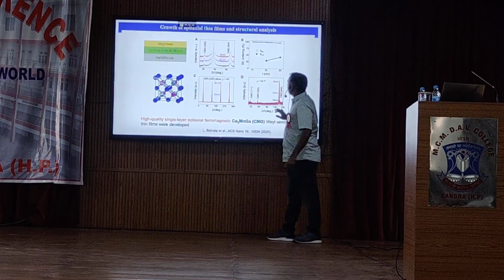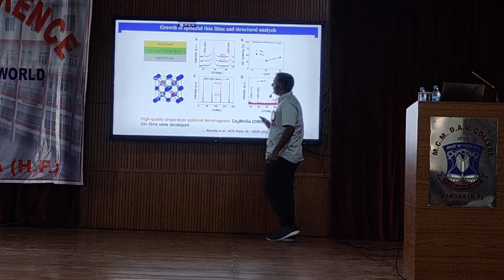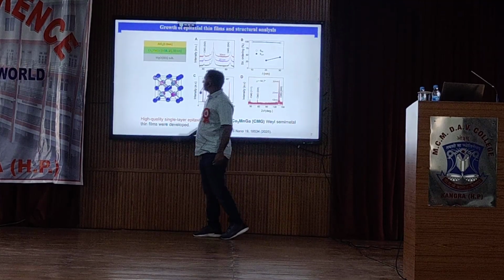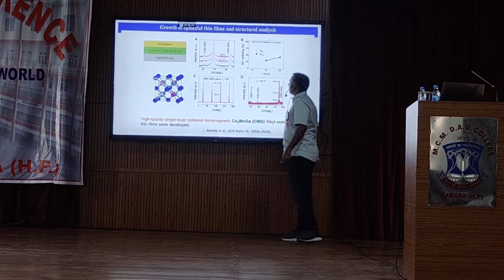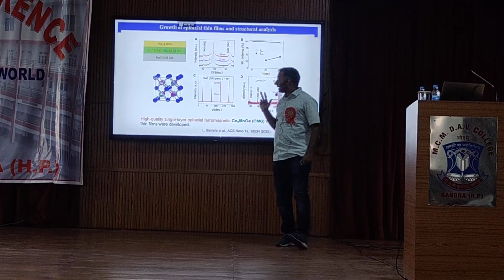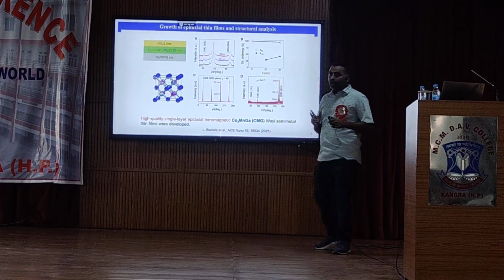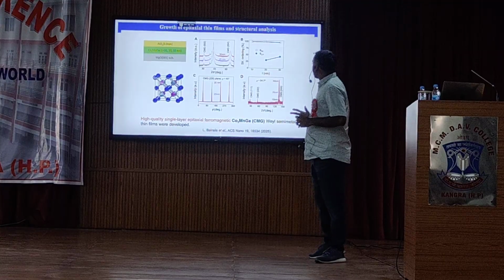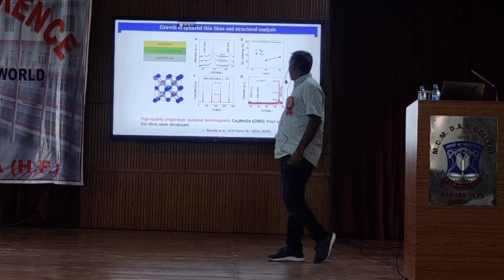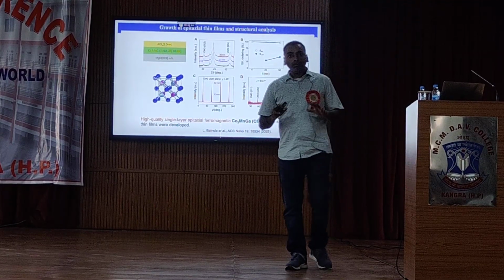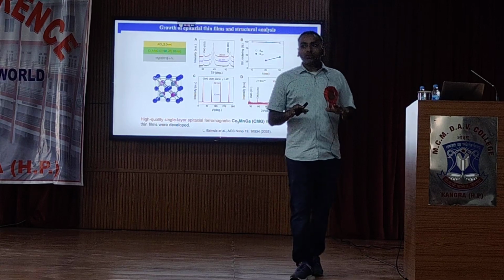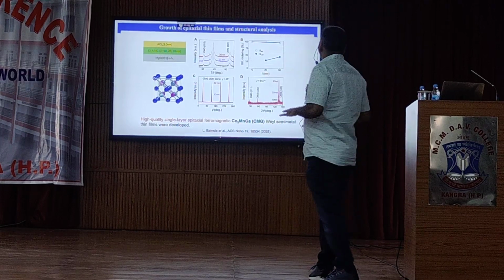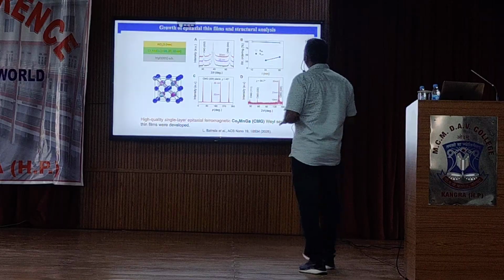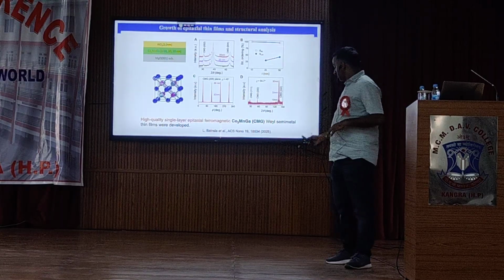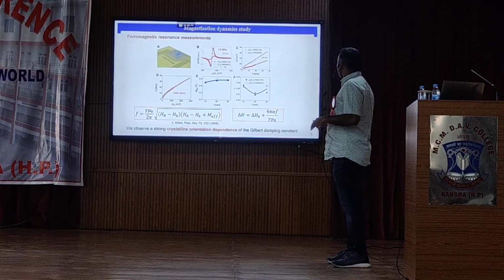Then we are interested in whether there is any disorder between manganese and cobalt sites. That we study with L21 disorder. The L21 disorder parameter tells us whether we have any antisite disorder between cobalt and manganese. And here, as you can see, you find some antisite disorder between cobalt and manganese. But still, it's better than previous reports from other groups. Then we do further studies.